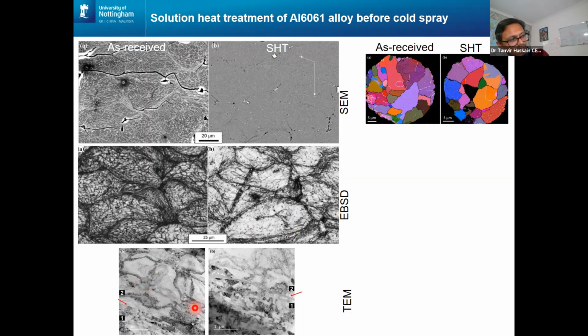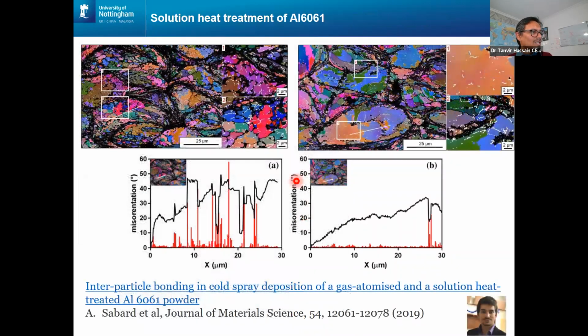boundaries. TEM images, again, as received and solution heat treated, showing more close bonding at the interface between two particles. We then took this work a bit farther and tried to understand what's happening within these particles. So that's an as received particle. These two are inset high mag images. This is a solution heat treated particle coating and inset images.